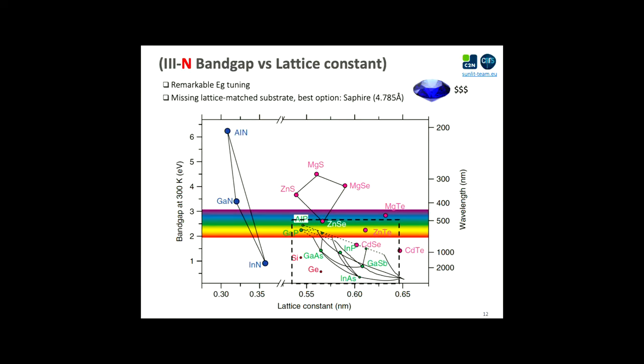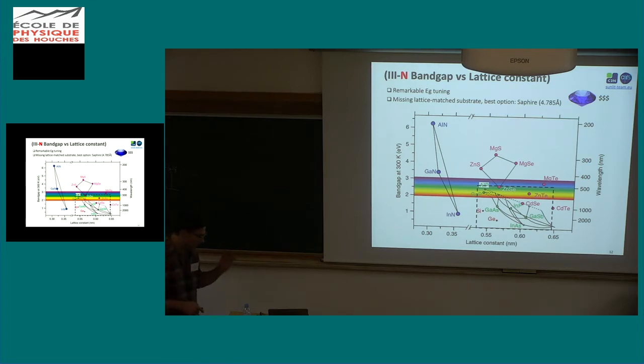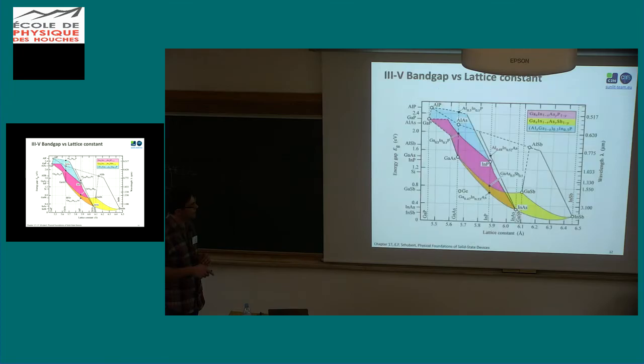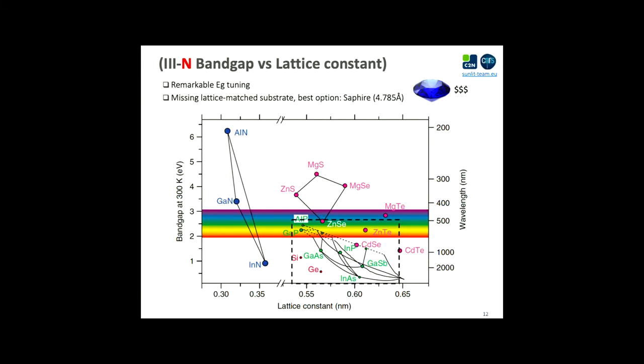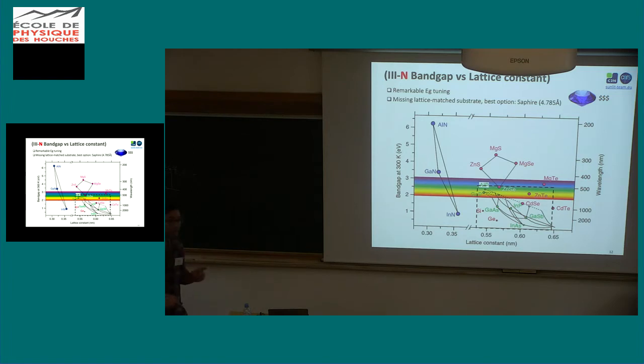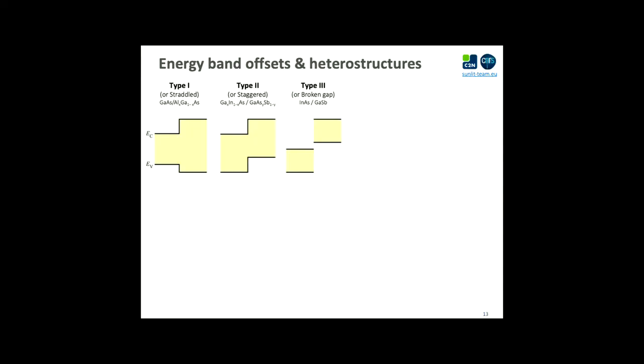So just a note on the fact that there is a particular class of materials called nitrides, where the fifth element will be nitrogen this time. And in this case, you can even scan a very, very large range of band gaps. Here I highlight it on the previous graph, so you see it's very, very large. The problem with these nitrides is that we do not have a lattice matched substrate on which we can grow them. At the moment we are using sapphire, although its lattice constant is not really close, and it's clearly expensive, so the quality of these materials is still not at the same level of the more conventional III-V.